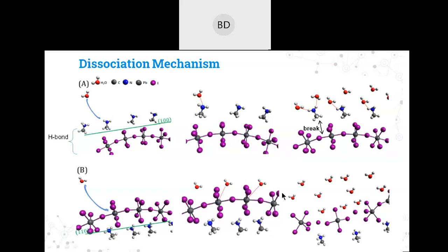And eventually, when the concentration is very high after a prolonged aging, most of the iodine bonds in the PbI6 octahedra are broken, and what we are left with is PbI2. So if you see, in both cases the final byproduct is PbI2 only, but the process through which the degradation proceeds is completely different in both.